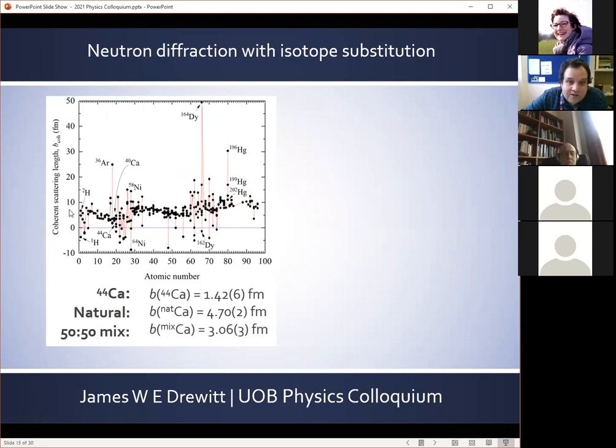And we can use this to gain insight, for example, on the calcium environment by applying the method of neutron diffraction with isotope substitution. This was a technique, as Bob mentioned, developed by Bristol's John Enderby, where we can take different isotopes of the same element. So in this case, calcium-44 and calcium in its natural isotopic abundance have quite a large scattering length contrast.